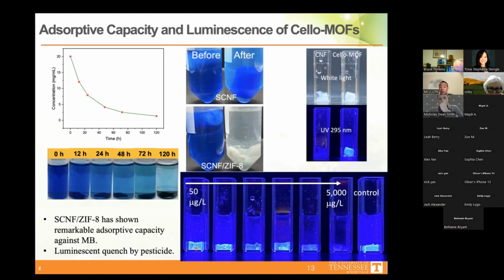And then we put a UV light on it, and you can tell that at a very low concentration it has really high luminescence, and gradually, with maybe a little bit of a hiccup right here, in general it gradually quenches with the absorption of the pesticide. And this is a control right here. It's really shining under the UV light. So based on this performance and observation, we can eventually build a sensor to tell how much pesticide is left in the aqueous system.